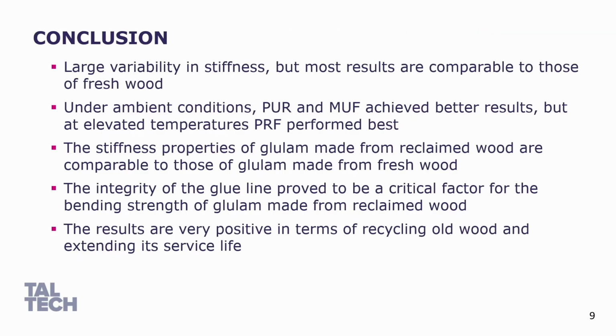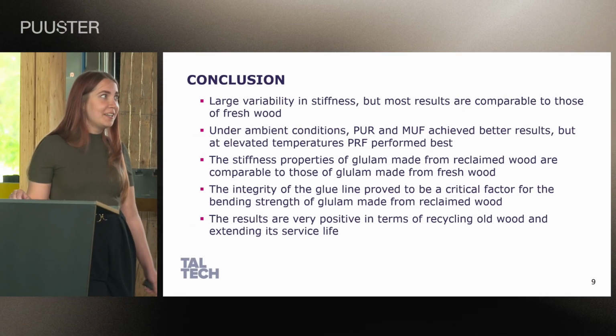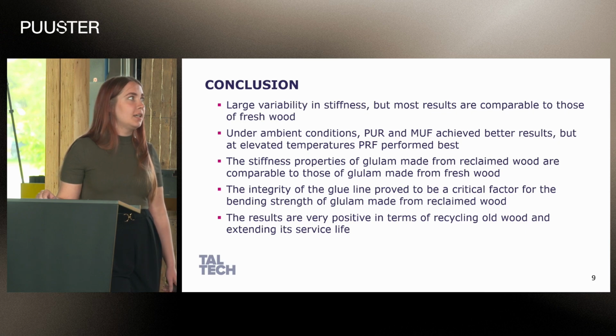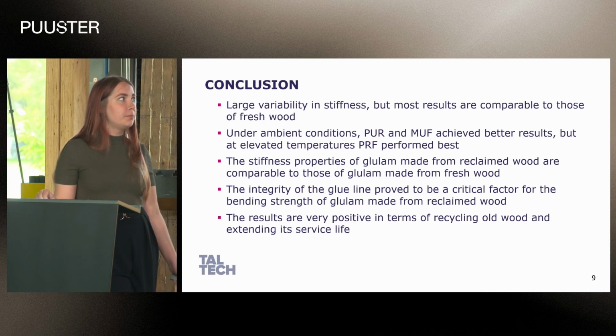And conclusion: there was a large variability in lamella stiffness, but most results are comparable to those of fresh wood. Under ambient conditions, PUR and MUF achieved better results, but at elevated temperatures, PRF performed the best. The stiffness properties of glulam made from reclaimed timber are comparable to those of glulam made from fresh timber.